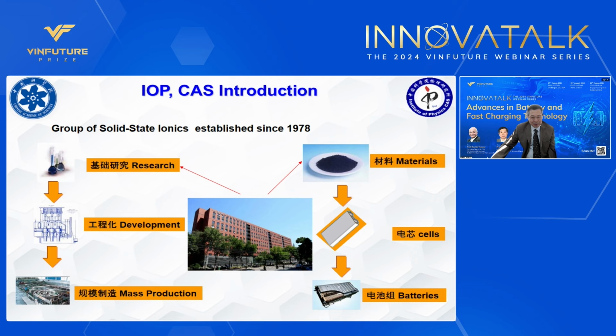Okay. So firstly, we have developed a very dense high nickel ternary oxide cathode material for the EV battery applications. We need to increase the content of nickel and decrease the content of cobalt to get a high capacity but lower cost, but the problem is the safety, the stability of this material. And then we decided to change the philosophy. We try to change the polycrystalline NCM 90 or 95 to very dense polycrystalline particles. To make it, we need to mix different elements, in very small amounts but very effective to decrease the primary particle grain, and then we can get very dense and very strong secondary particles for applications.